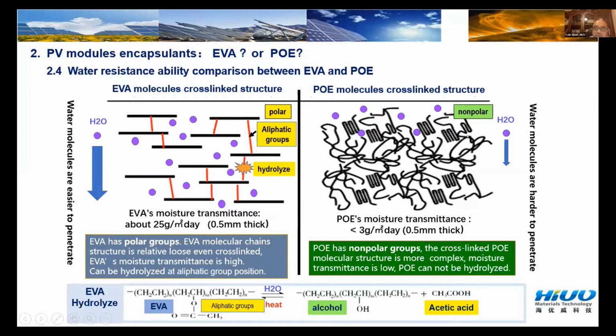So let's look at the polyolefin. The polyolefin, the whole system is a non-polar system. Their cross-link structure is like this. So the POE's cross-link structure is more complex and the moisture transmittance is low. So POE cannot be hydrolyzed because they do not have polar groups. So let's look at how EVA hydrolyzes. EVA hydrolyzes from this position. You can see with the heat and in a water-existing environment, it will be hydrolyzed to alcohol and acetic acid.